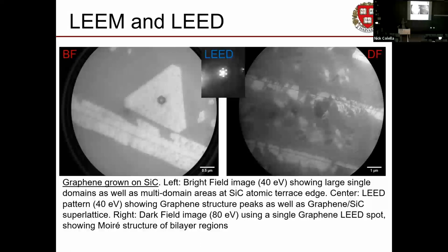Since we have a diffraction pattern, each one of these spots in the diffraction pattern, my pointer, is actually a full image. So we can take a little aperture, a piece of foil with a hole in it, put it in front of this pattern, mask off everything except for one spot, magnify it way up, and take an image of just the diffracted electrons, the ones that interacted with the crystal structure and got bent off to some funny angle because of physics.